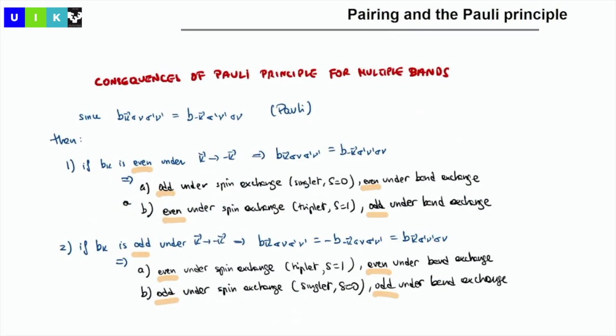So summarizing these general remarks about the role of the Pauli principle in the Cooper condensate, and considering a system that is not limited to one band, so multiband systems, this is in fact especially important for iron-based superconductors, where superconductivity is influenced by many bands, all the iron d bands near the Fermi level. So in this generalization, by imposing the Pauli principle, we have that if the Cooper pair is even under k to minus k,